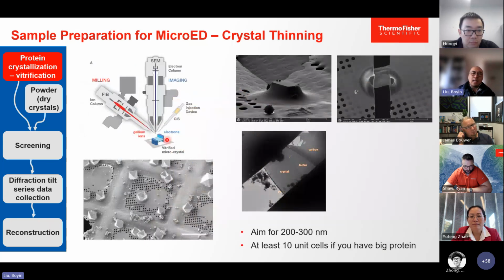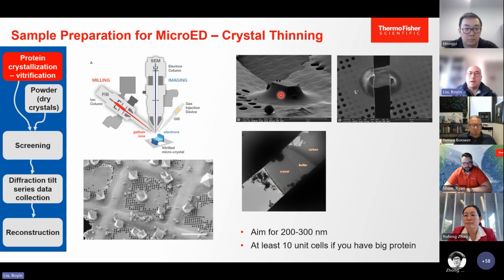And then in this slide, I want to talk about some differences from cryotomography. Basically, this is how a good sample looks. You need to have some buffer there to stabilize the sample, but in the meantime, the buffer can't be too thick, otherwise you spend lots of time milling. Then you can produce a very good lamella. Under the TEM, you can see the different layers: a protective platinum GIS layer, the crystal itself, buffer, and carbon.